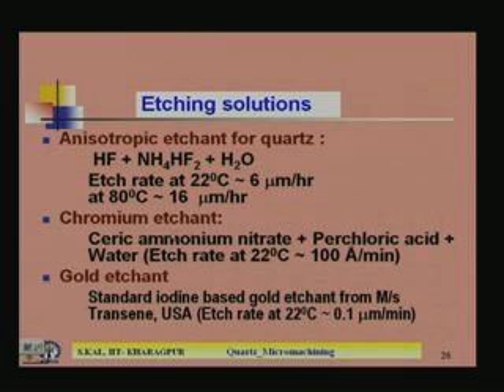Chromium etchant is also used, because the masking material is chromium gold. So, you need to etch gold as well as chromium. For chromium we use ceric ammonium nitrate plus perchloric acid plus water. This ceric ammonium nitrate, perchloric acid, water mixture will etch chromium with an etch rate of 100 angstrom per minute at room temperature, that is 22 degree Celsius.